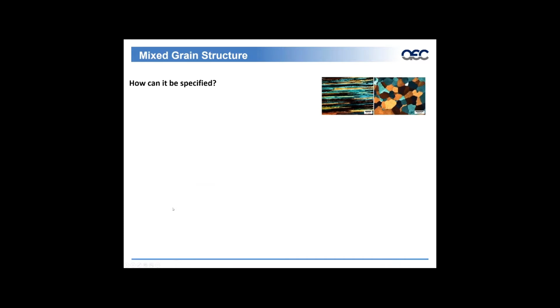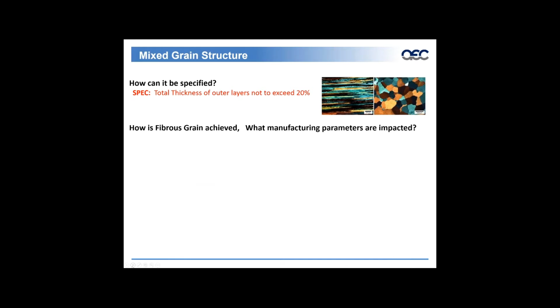So mixed grain structure, how can it be specified? There's many different ways to go about that. My experience has been the total thickness of the outer layer typically has a percent not to exceed. That percent could range by specification or by requirement, but for example, it may range from 10 to 20% or 25%, depending on the application, the performance requirement.